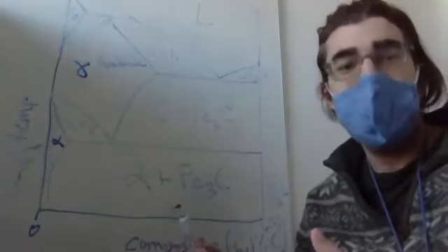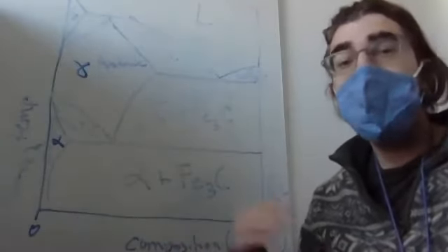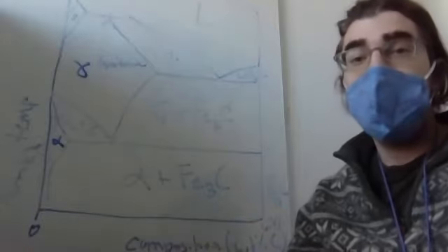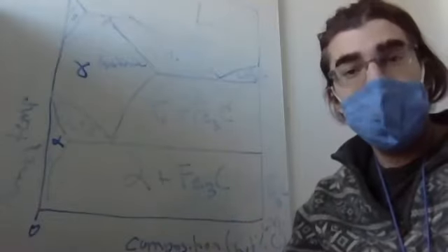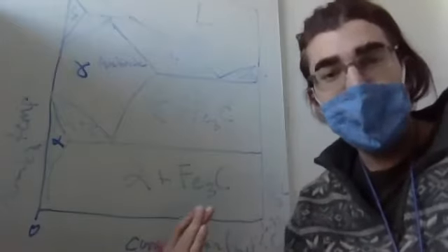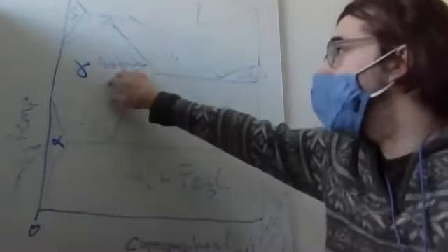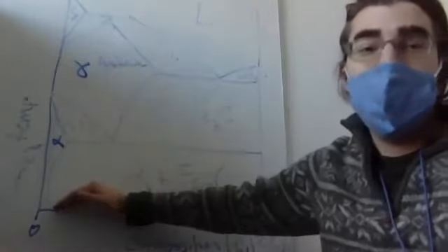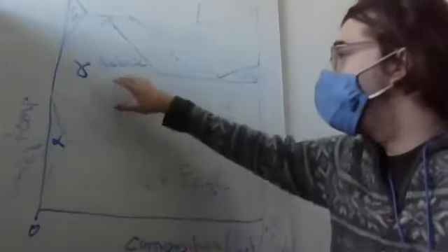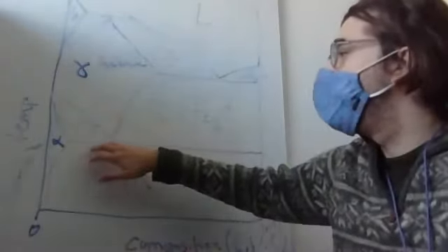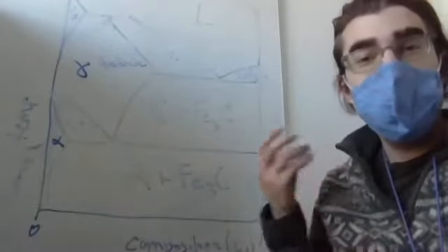The same thing exists with atoms and phases. So if you give atoms enough time, they will go to the thermodynamic rest state. But if you make atoms rush, oftentimes we can trap atoms in these higher energy states at room temperature. So one way we can get different microstructures is by the rate of cooling.